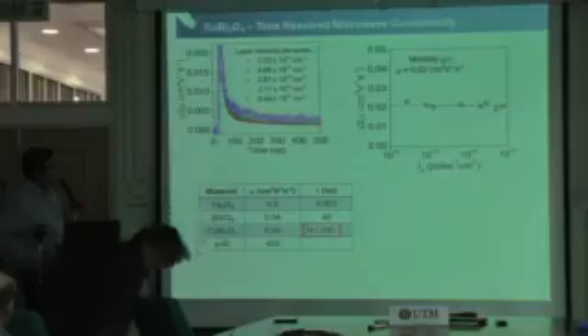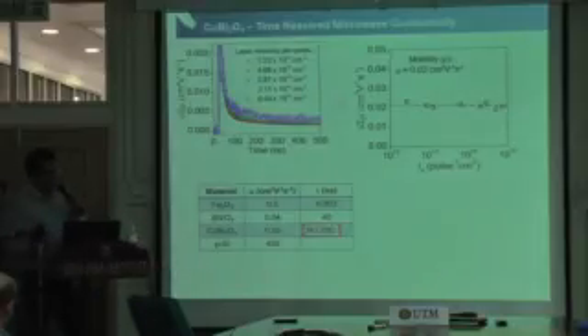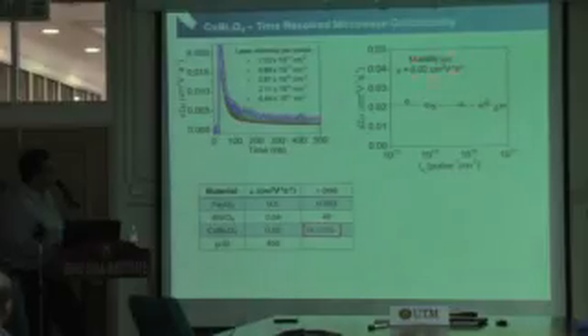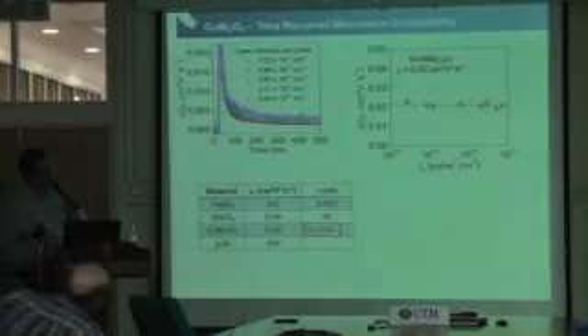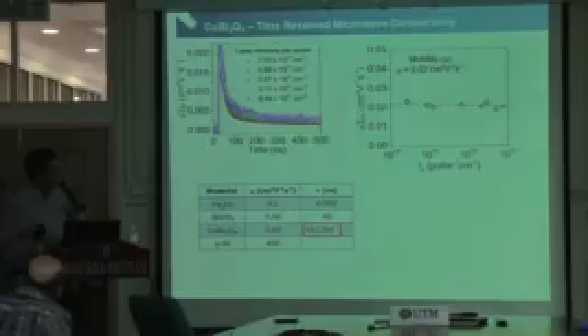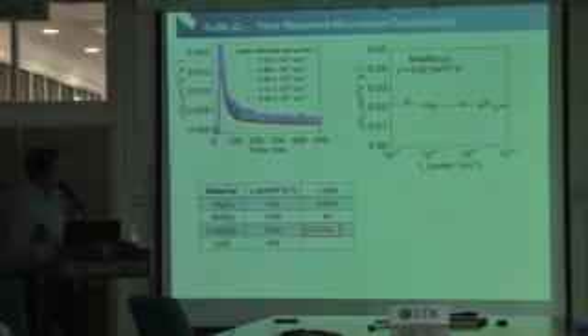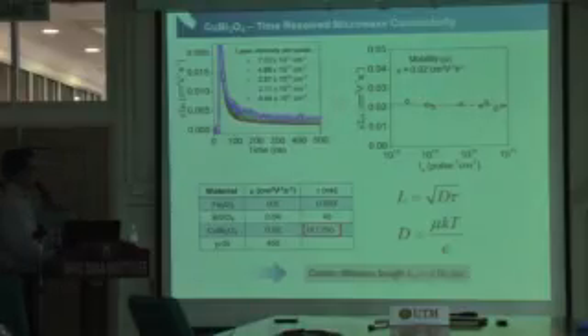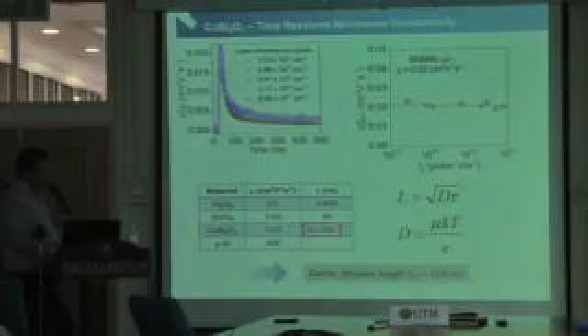We then also checked the carrier mobility of this film with the TRMC measurement that I explained earlier, and we get a mobility value of 2 times 10 to the minus 2. This is comparable to bismuth vanadate, and a carrier lifetime of up to 250 nanoseconds, which is really good compared to bismuth vanadate. All in all, the carrier diffusion length is about 110 nanometers.